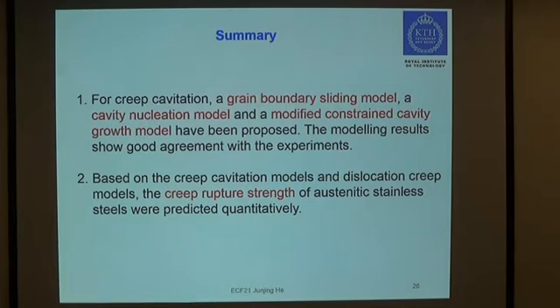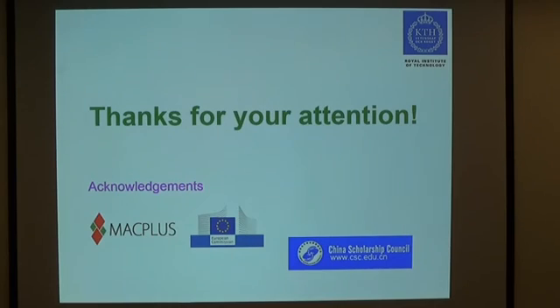Summary. For creep cavitation, a grain boundary sliding model, a cavity nucleation model, and a modified constrained cavity growth model have been proposed. And the model results show good agreement with the experiments. And based on the creep cavitation models and the dislocation creep models, the creep rupture strengths of austenitic stainless steels were predicted quantitatively. Thank you for your attention.